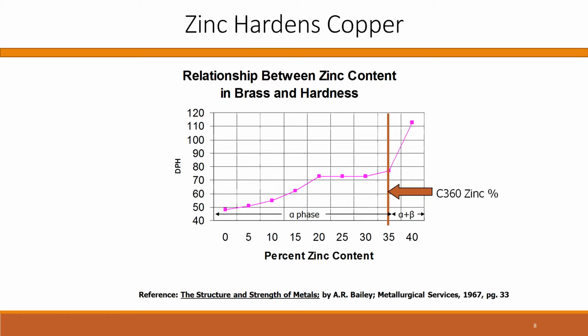The zinc content that we talked about is important for corrosion resistance and making the alloy harder and more machinable. You can see the impact of increasing zinc along the x-axis versus the hardness along the y-axis, or the vertical axis. As zinc content goes up, the hardness goes up, and it reaches a plateau after a while if all you have is a copper-zinc alloy. Once you pass 35% zinc, it really shoots up high. And alloy 360, which is still the dominant leaded machining alloy on the market, is at that 35% zinc level. So you've got a pickup. Actually, it's a little bit above the 35% zinc. So you've got quite a rapid increase in hardness that helps with the machinability.